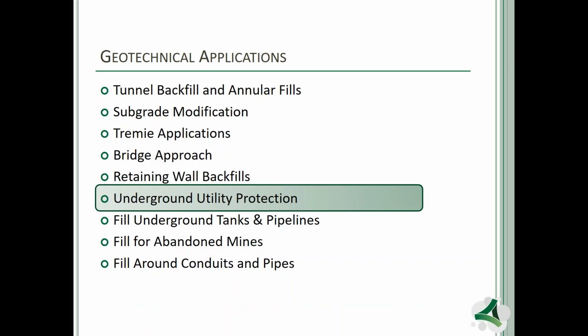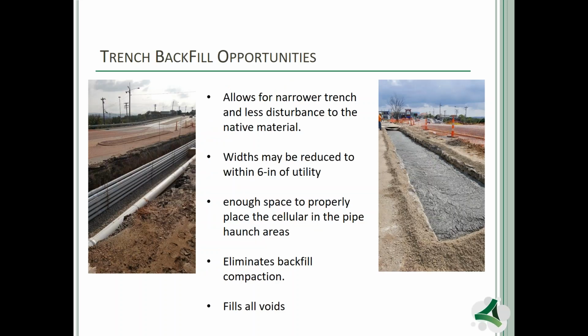When it comes to underground utilities and the placement of the cellular concrete with those, your trench configuration for utilities is drastically reduced in width, because all we need to get the cellular concrete into the haunch areas of the utility is no more than 6 inches on either side of that utility, to make sure we have the appropriate compaction. Again, the material is self-compacting and self-leveling. No compaction is required, no vibrating rods either, and it will fill every nook and cranny within the project. Because you're going with a much narrower trench than you normally would, you're also saving some money on that. And in some cases, you might be able to reduce your right-of-way scenarios on your project.